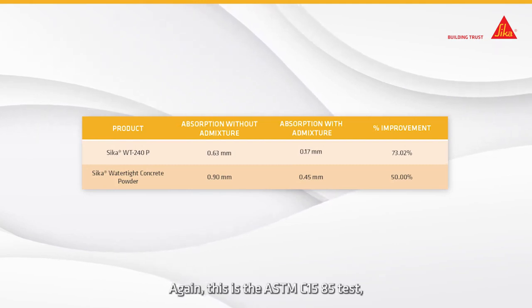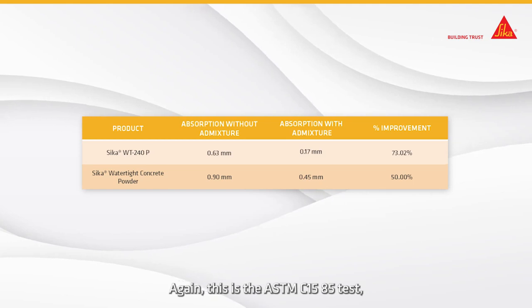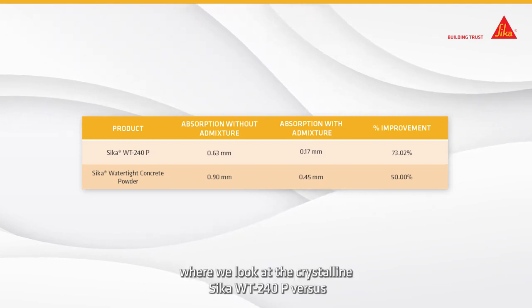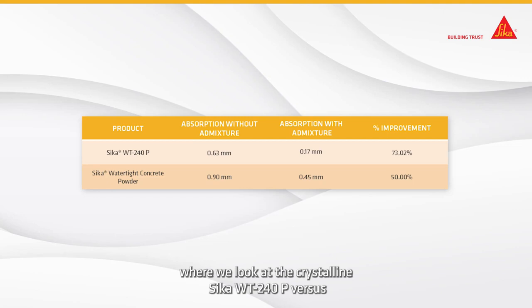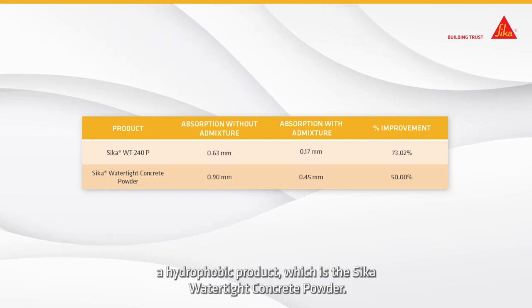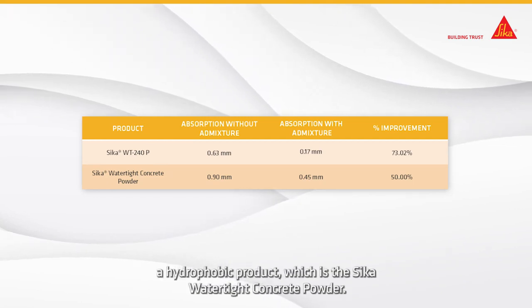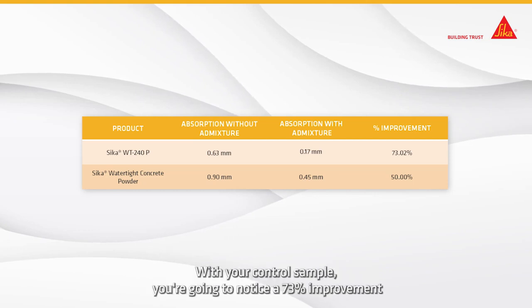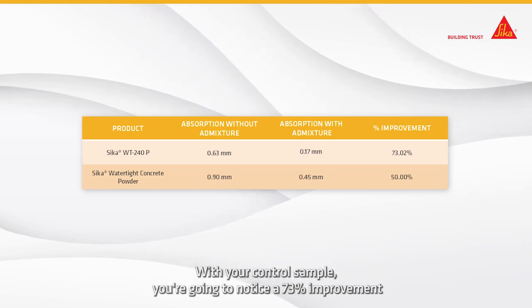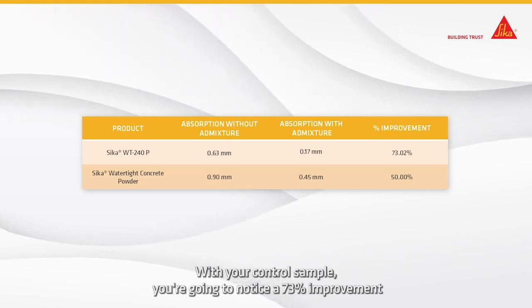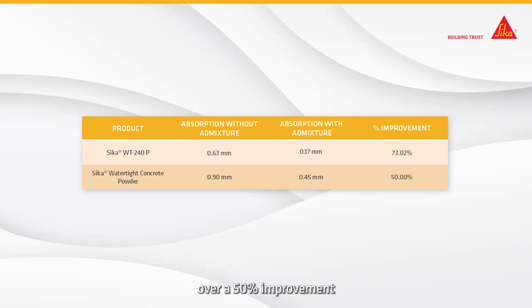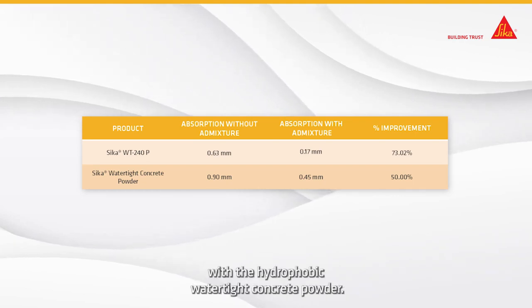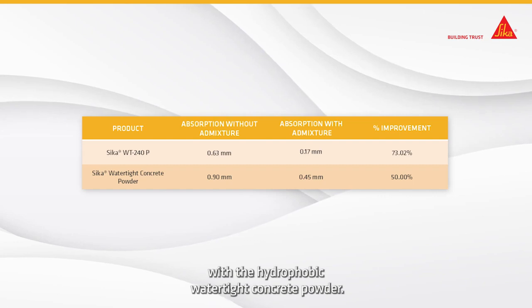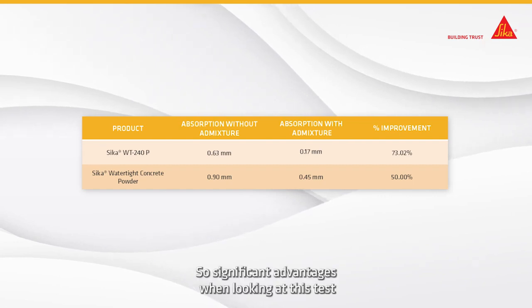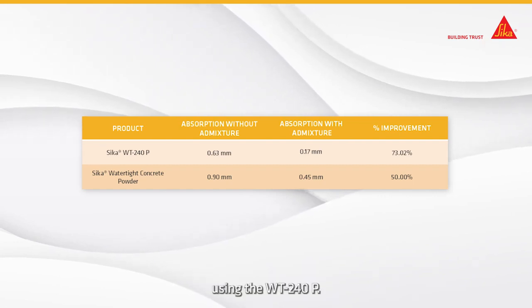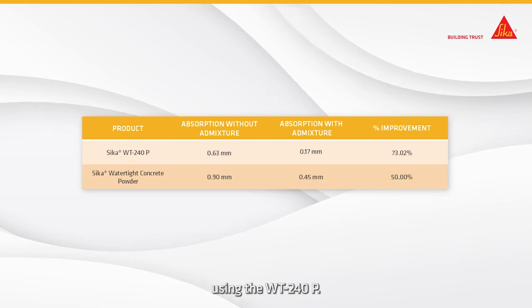Again, this is the ASTM C1585 test, where we look at the crystalline Sika WT240P versus a hydrophobic product, which is the Sika watertight concrete powder. With your control sample, you're going to notice a 73% improvement over a 50% improvement with a hydrophobic watertight concrete powder. So significant advantages when looking at this test using the WT240P.